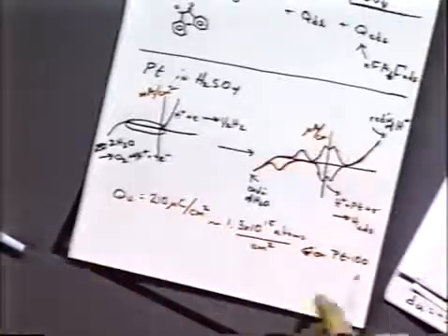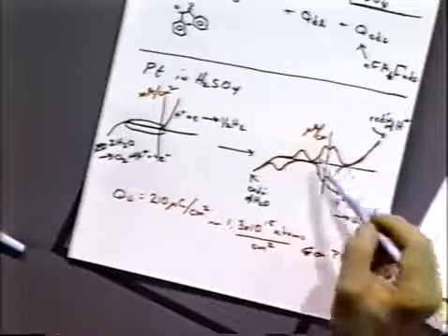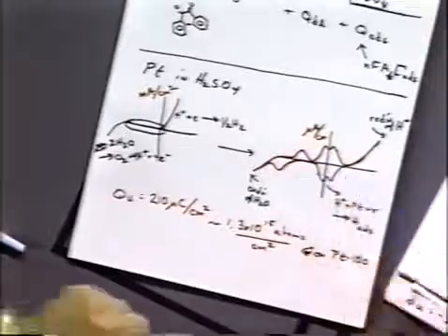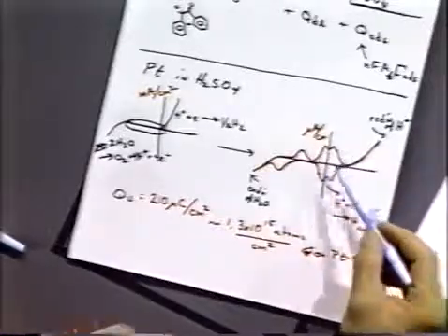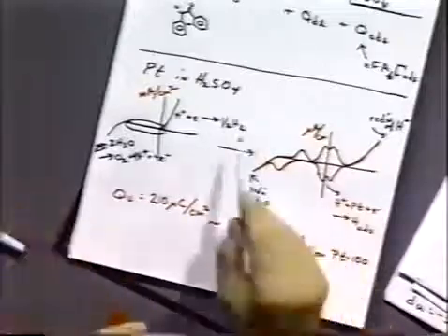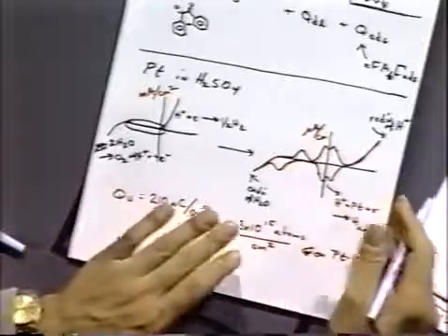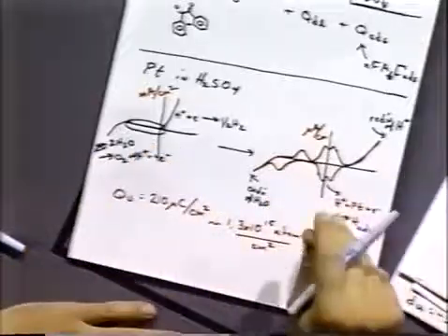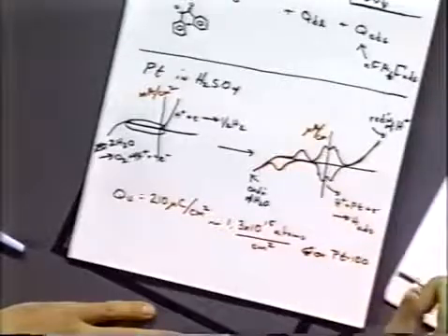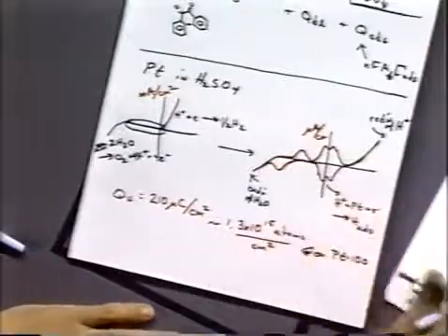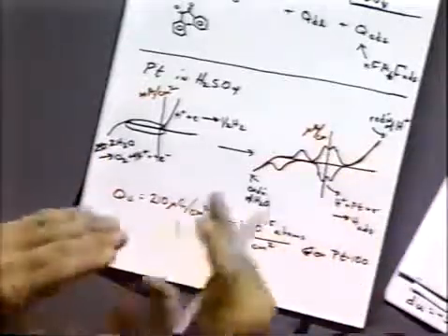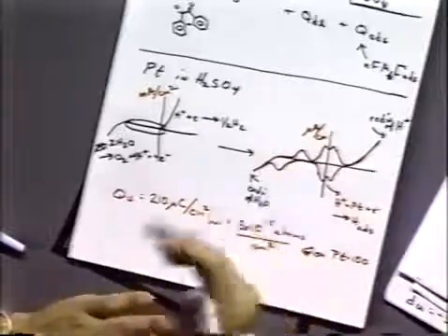It depends, these wave shapes actually depend on the type of platinum crystalline surface that's exposed to the solution and some other things. And they're very dependent on the purity of the solvent. If you have even tiny, tiny amounts of impurities, organic impurities, these peaks shift around and are not in the same place or not as large, or they're shifted. And that is a good diagnostic test for purity of the solution. So people often use the shapes of these peaks and the sharpness of the peaks as indications of solution purity or electrode polishing, good electrode polish.